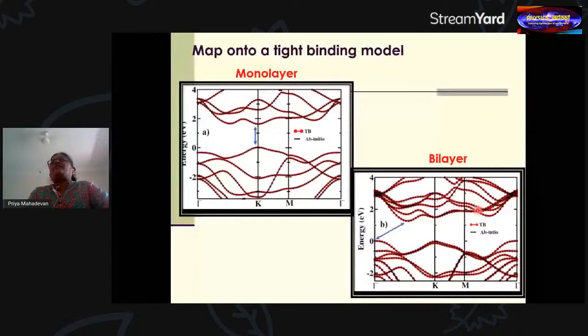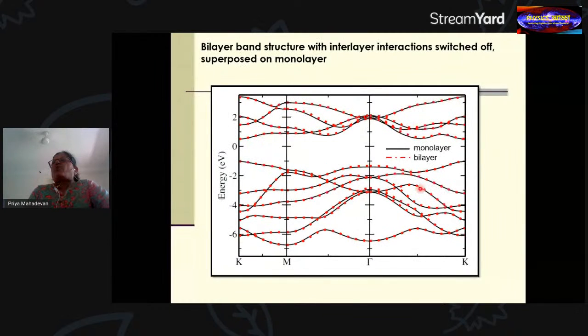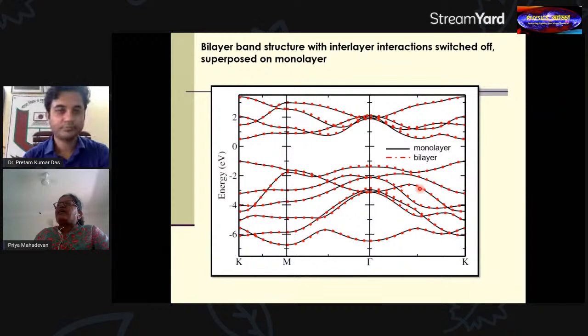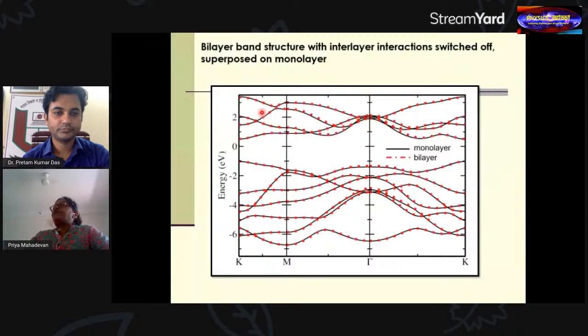And what do I do? I recover the monolayer band structure. So all the changes that are happening, I have control over, because I know what the interactions are. Even though these are materials called van der Waals materials, there is a small covalent interaction between the layers, but it's pretty small. And that is what is reflected over here, because if I switch off these interlayer interactions for the bilayer, what I recover is essentially the monolayer's energy eigenvalues. So now I understand what exactly is determining the changes in electronic structure when I go from monolayer to bilayer.